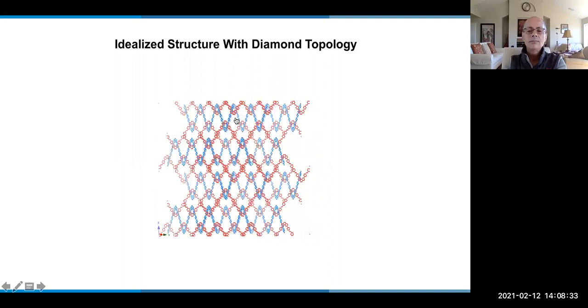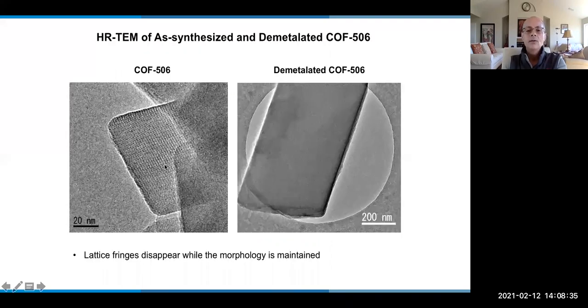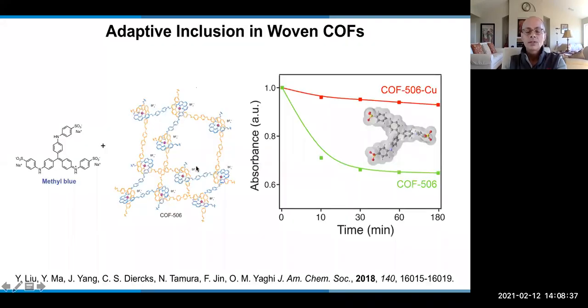I just want to show you that, in fact, the structure is dynamic because you can put a molecule that's much larger than the pores of the metallated into the non-metallated, okay? This molecule is trying to get into the pores and can't with the metallated, but when you demetallate, it goes right in. And that tells you that the pores are stretching to accommodate